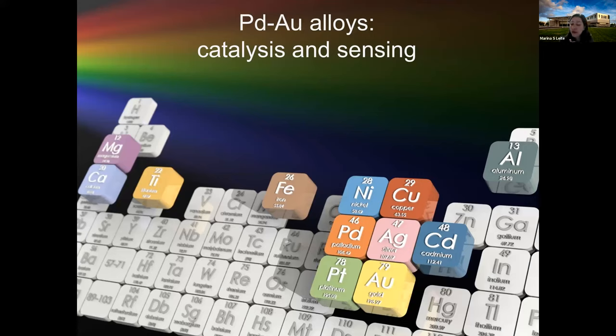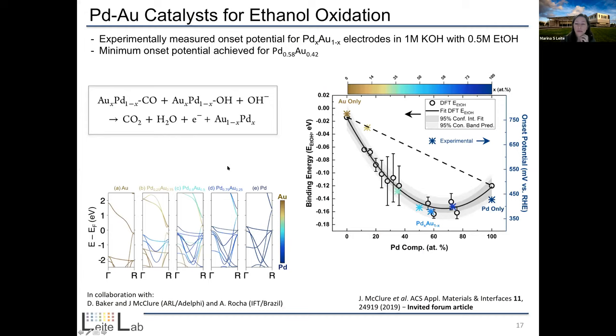We have also looked into other metals. So for instance, the combination of palladium and gold has shown to be very promising for both catalysis and sensing. So I'll show you one example in catalysis, primarily because it's also a collaboration with Alexandre Rocha and folks from Army Research Lab back in Maryland. And essentially we could show that if we use a combination of palladium and gold, we can actually have a boost in the performance of the ethanol oxidation reaction.